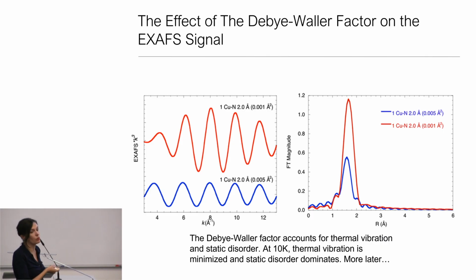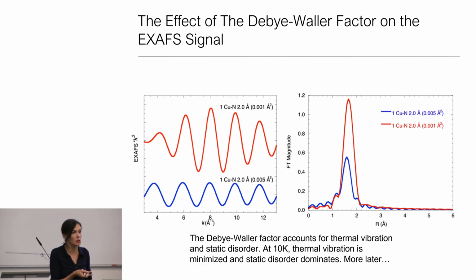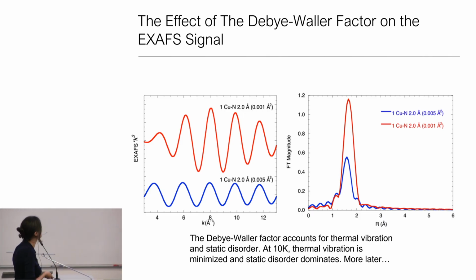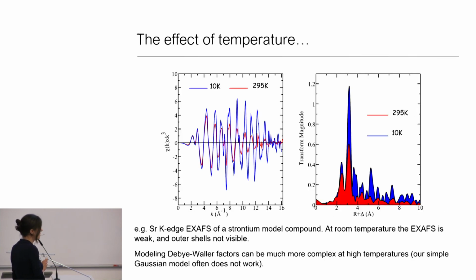And now you can see why coordination number is so uncertain, because maybe it's disorder, maybe it's a change in coordination number. I don't know. My tip is look at your pre-edge. Maybe it helps you. That's just a reminder. Okay, but let's talk a little bit more about the Debye-Waller factor here. Here I'm showing you what happens as we go from 10 K to room temperature on the same sample. You can really see that as we raise up to room temperature, the red spectrum is significantly damped. So if I really care about getting good structural information and good long-range order, I want to do EXAFS at low temperature if I can.